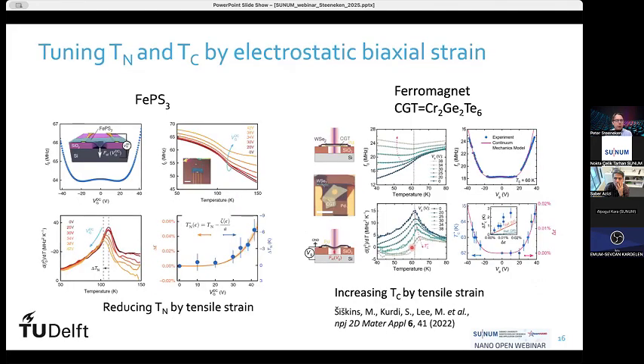So we can do more. We can also add strain. One way to add strain is to put an electrostatic force. We generate a voltage between the suspended membrane and the substrate, and then we can pull it down and look what happens to this Néel temperature. So we can actually shift this Néel temperature by strain.